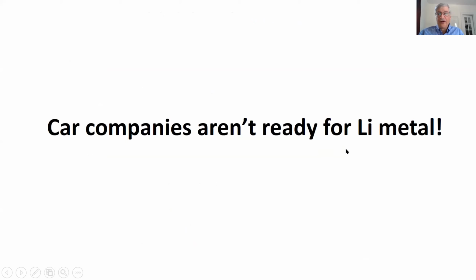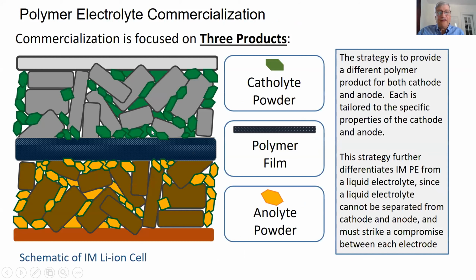However, car companies aren't ready for lithium metal. So we've got to go back to lithium ion. And here's again where the advantage of a solid polymer electrolyte is strongly evident. So these are the so-called cathode particles, for example, the transition metal oxide. These are the anode particles. You have to electrically wire these things to the battery. So you have to have a pathway for the ions to get in and out. So you actually have a mixture of your electrolyte with your electrodes. And in a regular lithium ion battery, you have the same liquid electrolyte that soaks through the entire thing.